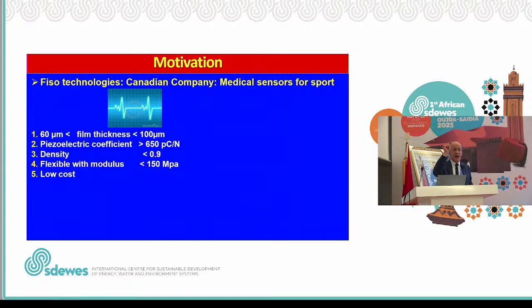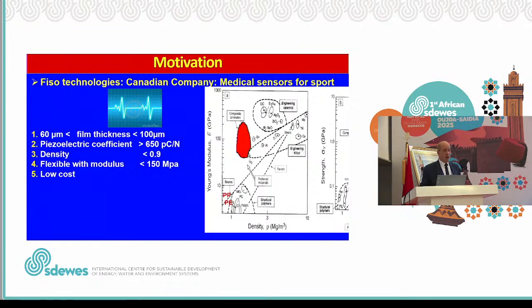We need a very low density, lower than 0.9, and we need a material that is very deformable, because if the material doesn't deform, then you cannot measure the heartbeats. So a material that is very sensitive to small deformation, and low cost. So if you look at existing materials that have at least a very low modulus. Modulus is resistance to deformation. A material that has a very low modulus is very deformable. A material that has high modulus, you cannot deform it.